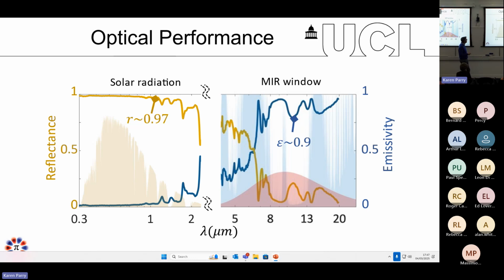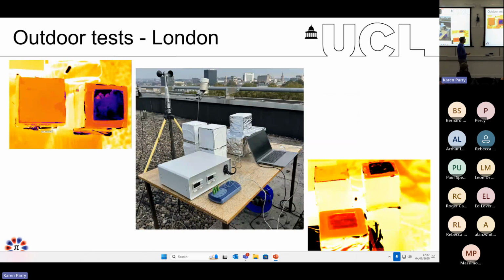Now, we experimentally measured our system, and we found that the solar reflectance is about 97, 98%, which is basically better than the best metal reflectors. We have an emissivity that exceeds 0.9. And we also took this in the field. This is the roof of the Mallet Place Engineering building at UCL, where we have our own weather station. And we tested this under real conditions, in outdoor conditions. This is, by the way, the fingerprint of our sample under an MIR camera. And this is a commercial white paint, where you can see evidently that our sample is at a substantially lower temperature.